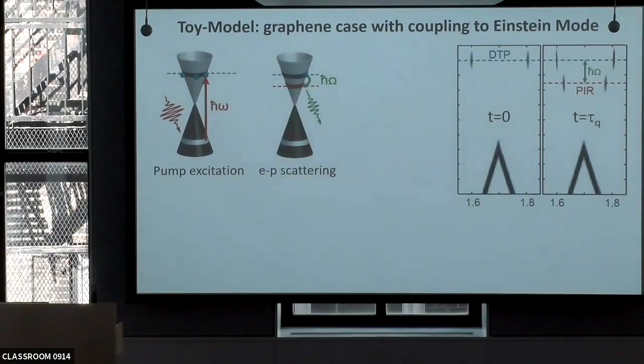Graphite will be the sample. Graphene is still used as a model, just a toy model to explain the idea. So the idea would be to come in with a pump. It's again 1.5 eV, just because it's the same photon energy coming in, 1.2 in this case. Just go and populate states above the Dirac point, and then wait to see when they relax by emitting a phonon. And what it means is, if I start off with a graphene sample, which is populated up to the Dirac point, through the optical excitation we create states above EF at about 0.6 electron volts, say.